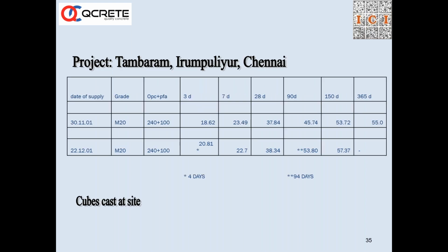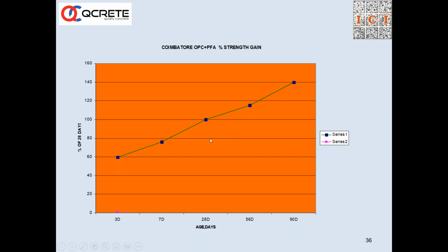So this was one of the cubes cast on site, on a church site in Chennai, and we can see the jump between 28 days to 365 days, which is it has jumped from 37 to 55 MPa. This is fly ash from Ennur near Chennai. Several, I can say thousands of results, each result is an average of 3 cubes, was taken from Coimbatore, the fly ash from Tuticorin, and several brands of cement, and we can see a significant jump of 40% between 28 days to 90 days.